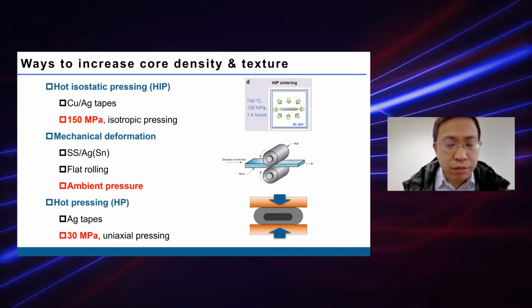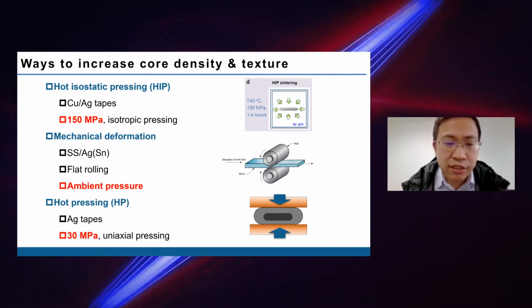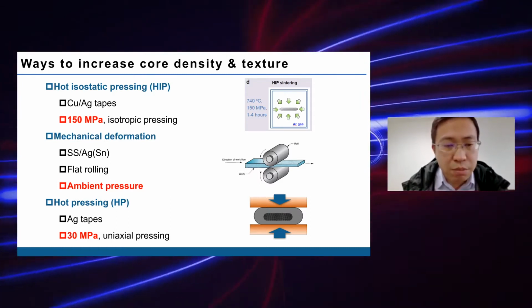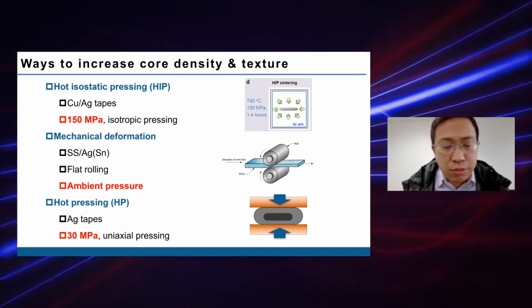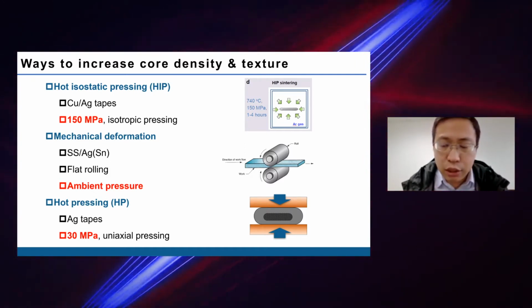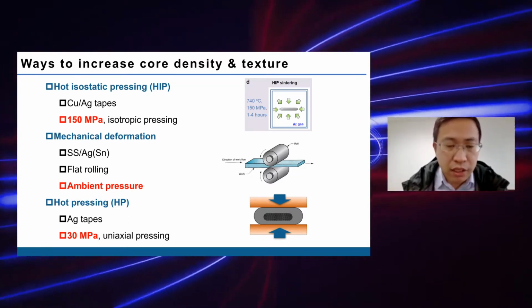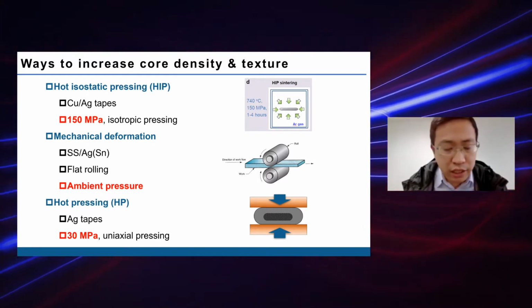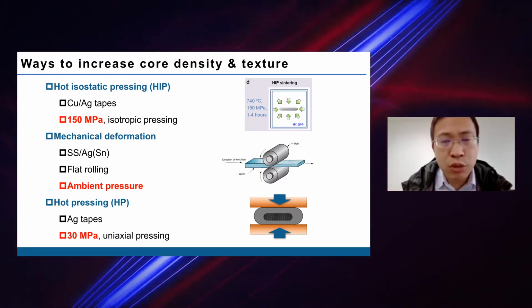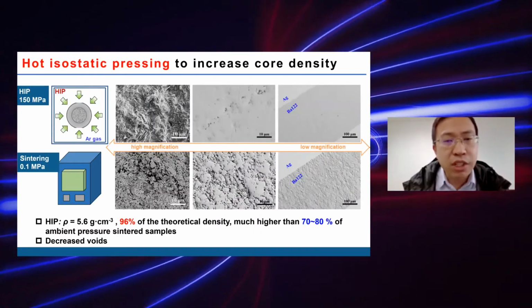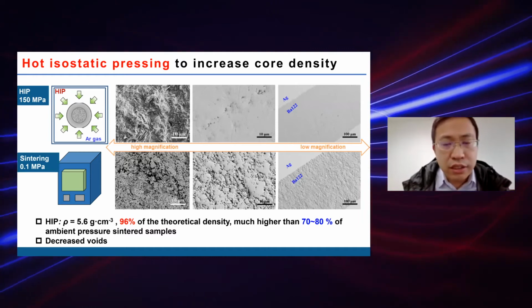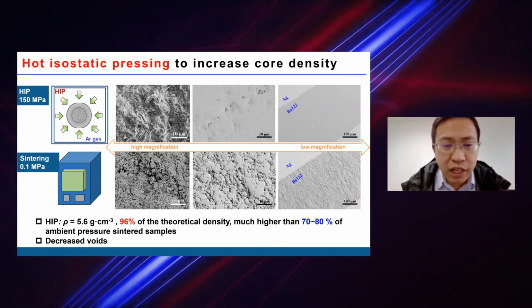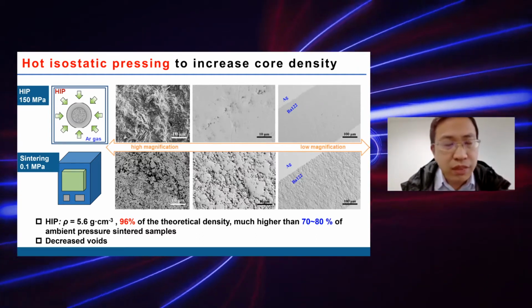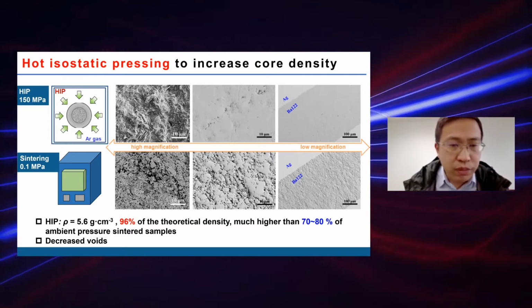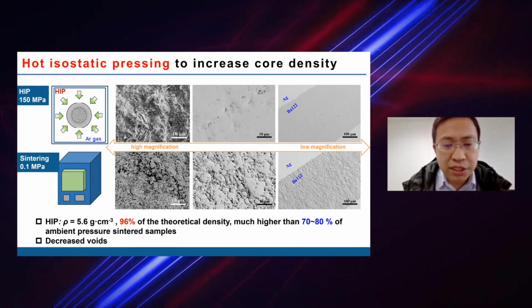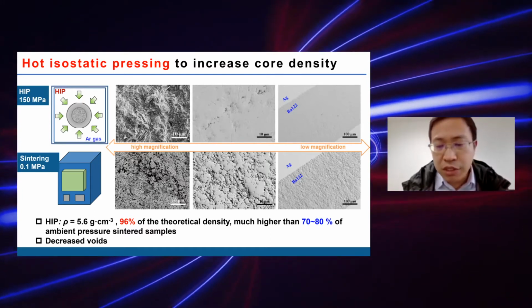especially the flat rolling process to introduce c-axis texture. This one can sinter at ambient pressure. The third one is a hot pressing process, where the pressure is only 30 megapascal, and we can get a very high c-axis texture. I will first talk about hot isostatic pressing. As you can see here, the cracks and voids are largely decreased in the HIP wires and tapes. The core density can increase to 96% of the theoretical value, which is much higher than the low one.